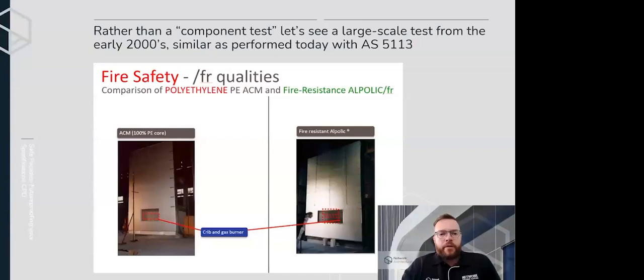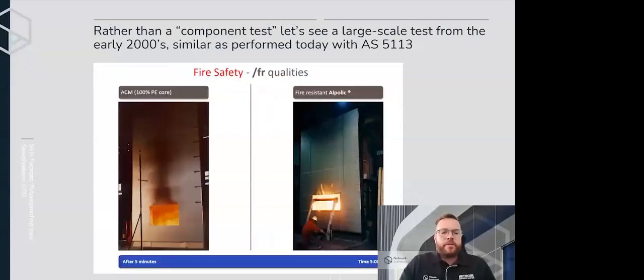So again, instead of a component-only test, we're actually going to look at a large-scale test. This was performed in the early 2000s. On the left is a 100% PE core aluminium composite panel, and on the right is our ALPOLIC FR. On the left, you can see the polyethylene panels are actively starting to contribute towards that fire, giving off that toxic black smoke. On the right, with the ALPOLIC FR, nothing's starting to happen yet.